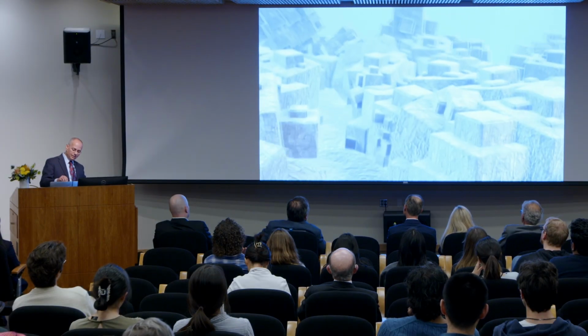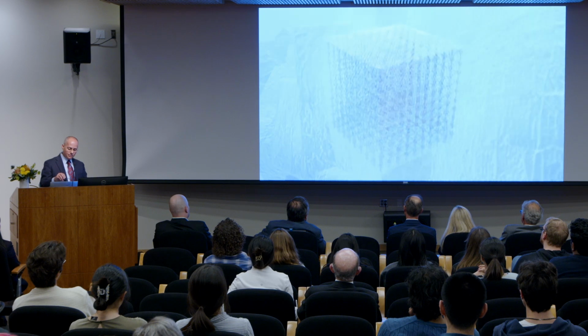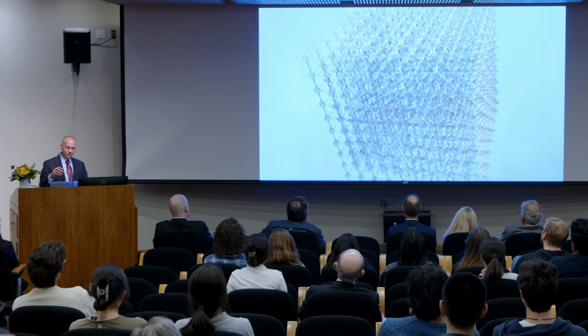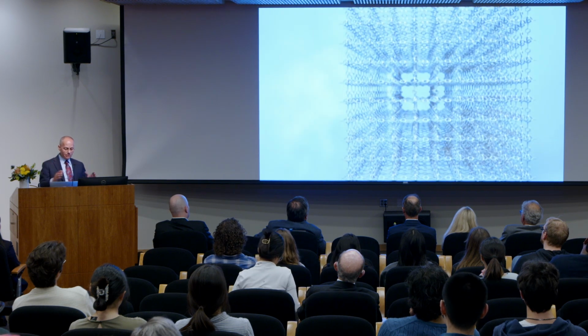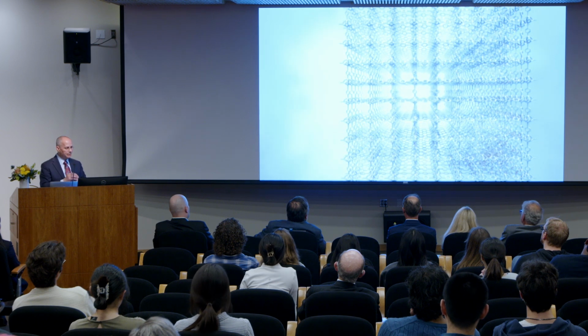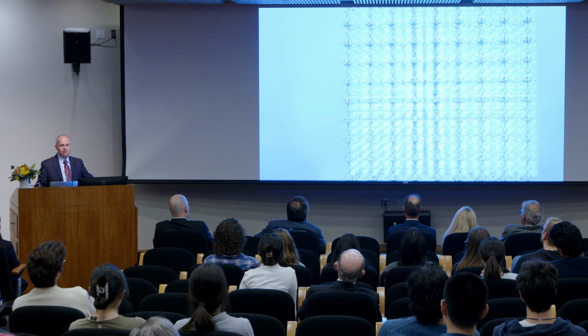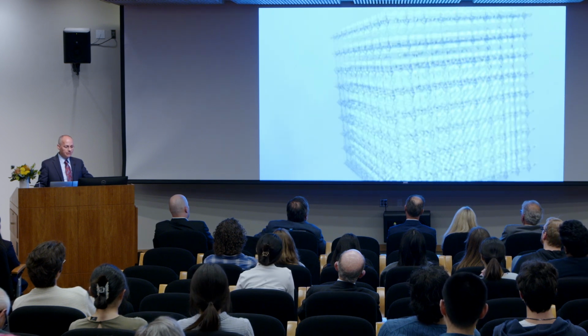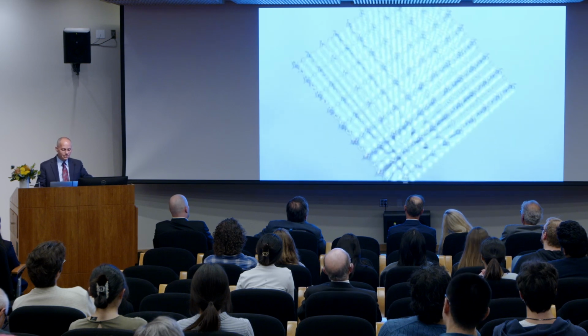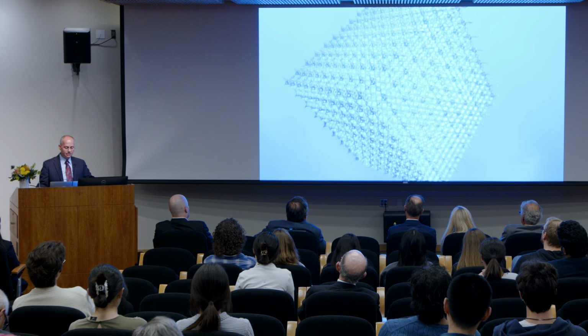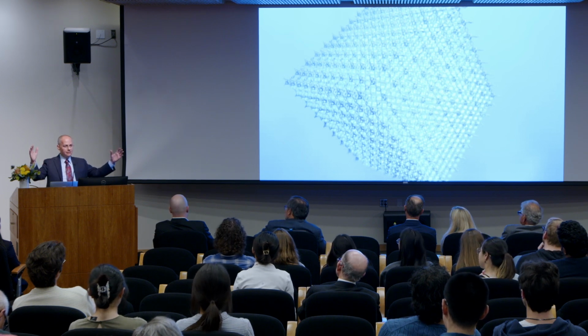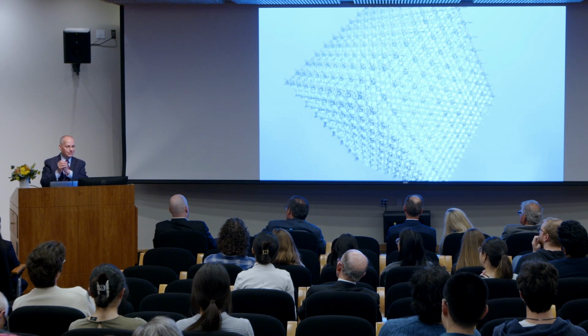This is what the materials look like. They're crystalline, and that means they have well-defined structures, and this is the way we can see them with our naked eye. But if I zoom in on the molecular level, you will see that they are constructed from joints, metal oxide joints, and organic linkers, to make open structures. And you can see the gases can then be stuffed inside by virtue of their attraction to the internal surface sites that I talked about in the previous slide. So that means I can take gases that fill a very large volume and compact them into a small volume, and that makes hydrogen storage a potential reality.